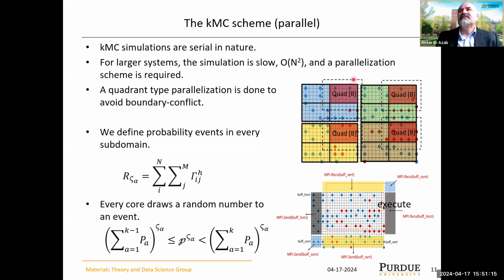This is illustrated here by dividing the surface into subdomains, and then each domain is broken into 4 quadrants here. And then you could think of this as an image, but it is not an exact image. When we do parallel execution, we search for these events happening in one quadrant at a time, and that is repeated in all subdomains. And then in the next step, we look at another quadrant and a third quadrant and so on. There is a little bit of bookkeeping here because you have to resolve events at boundaries, but that is taken care of by looking at quadrants as opposed to events happening at the subdomain as a whole.